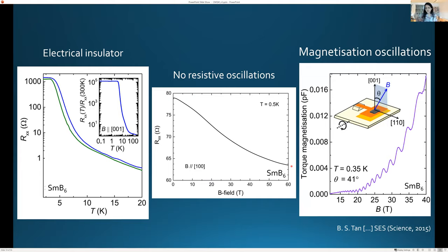At that point, we decide to measure magnetization just to see what the magnetization does, not expecting to see what we saw, which was very large amplitude quantum oscillations against the background of magnetic torque. So nothing has been subtracted here. This is just the magnetic torque, as I mentioned, which one obtained.